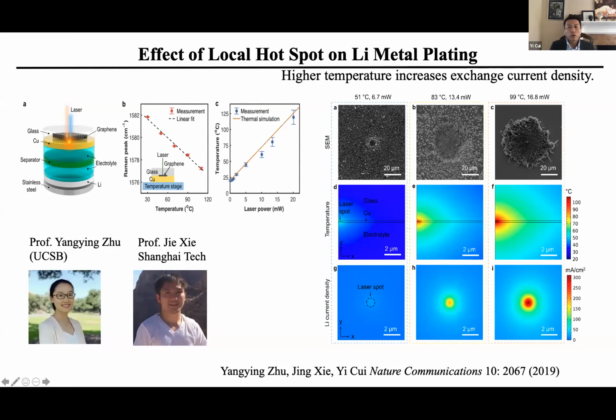Under this condition, the top row is the SEM during lithium plating, at the spot where you have higher temperature. When you have the laser heating on the backside, you can see there's a lot more lithium metal deposition taking place locally. Through careful study and thermal simulation, we found that this higher temperature local hotspot increases the so-called exchange current density and increases the kinetics of lithium deposition a lot more. So you can locally amplify the deposition using temperature, and that can cause potential shorting of the batteries. We want to point out that this temperature inhomogeneity can cause quite a complex effect in lithium metal battery charging.